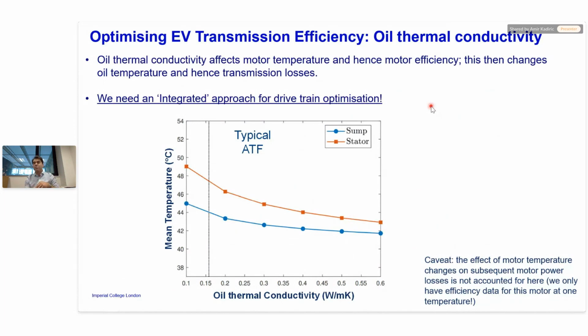We struggle to find published figures on the effect of temperature and efficiency of the motor. So what we've done in this particular model, we do include the heat exchanges in the motor and the efficiency of the motor, but it's at one single temperature and it's from published figures. We don't model it ourselves. But what we can predict is the effect on the temperature of the motor of change in the thermal conductivity of this oil. And you see that in this curve.